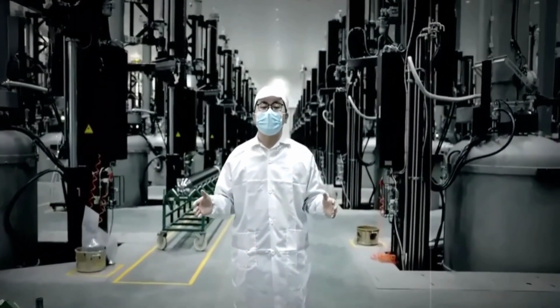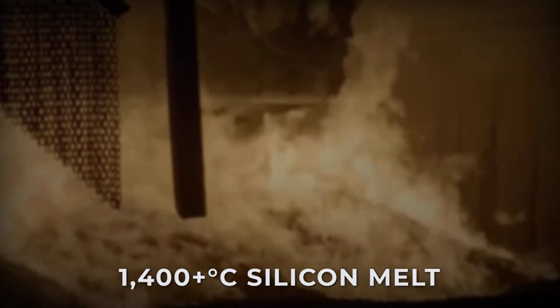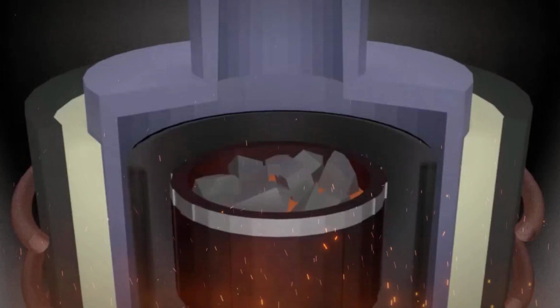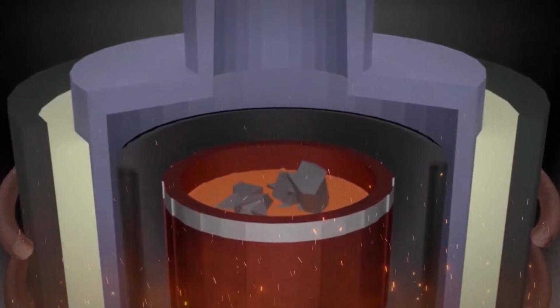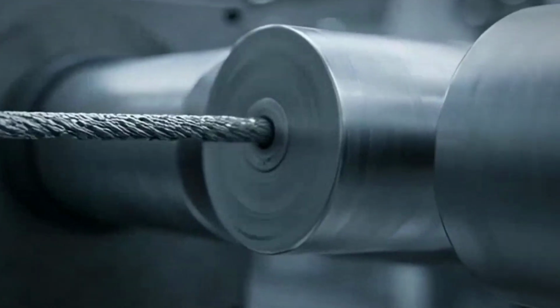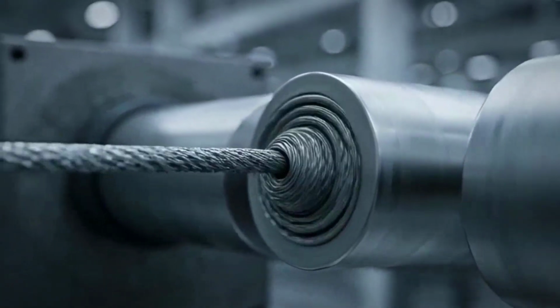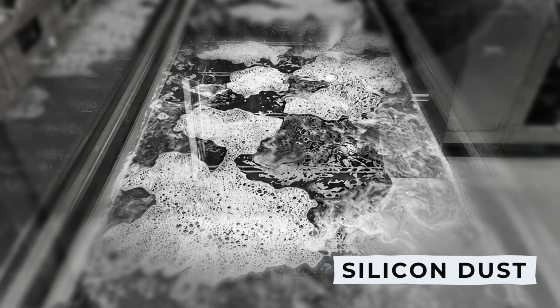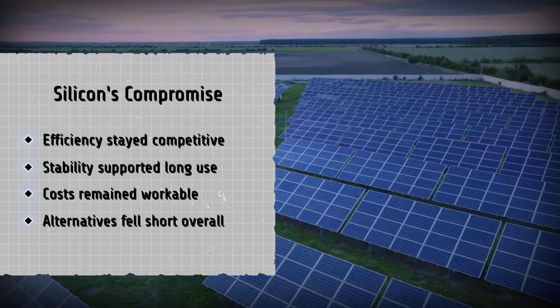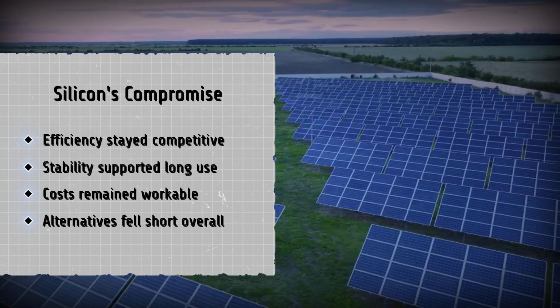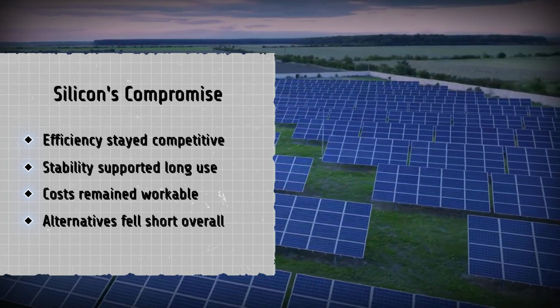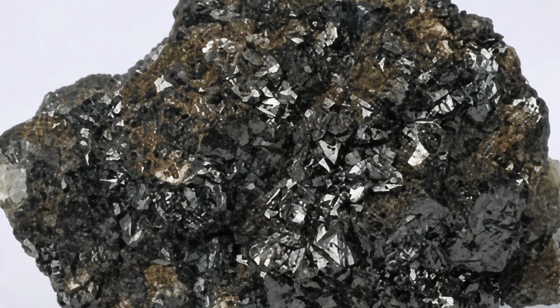And getting there is brutal. You melt raw silicon at over 1400 degrees Celsius, hotter than most lava, grow it into a single crystal ingot, then saw that ingot into wafers with diamond-coated wire. The sawing alone turns a large share of your silicon into dust. For decades there was no alternative because nothing else came close on efficiency, stability, and cost at once. Which brings us to the rock.